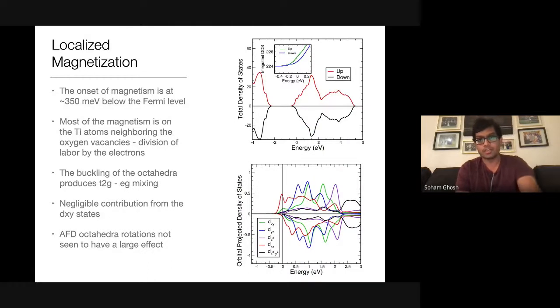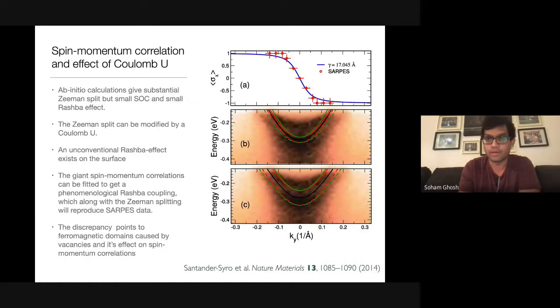So this is a picture of the magnetization. It is quite localized. It's only on the surface, and only one part of the electron states available contribute to it. There are some additional complications, but we showed that this is the main picture. Now, one final thing that you can do is put whatever energy levels you have and the spin splitting results on top of experiments, and you will see that there is a very good correlation.